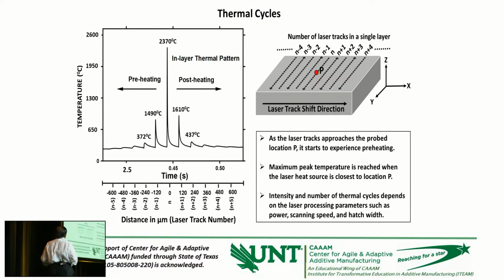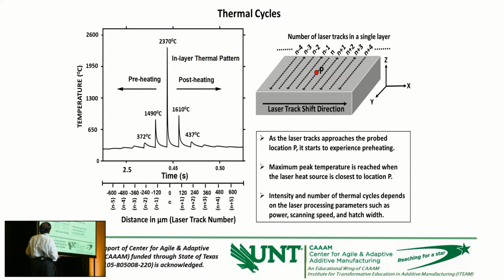So you can generate the heat cycles in each layer, and assuming that whatever temperature history is seen by this point can be seen by any point anywhere, that's how we repeat things. As you see, under the given condition, at any point in the layer, the temperature around it up to the second, third track drops down substantially. And at the fourth or fifth track away from this one, on both sides, the temperature drops pretty low. So that is how we track the temperature. Some of these temperatures rise as high as the melting temperature, whereas some of them are high enough to cause solid state transformation within the processing.